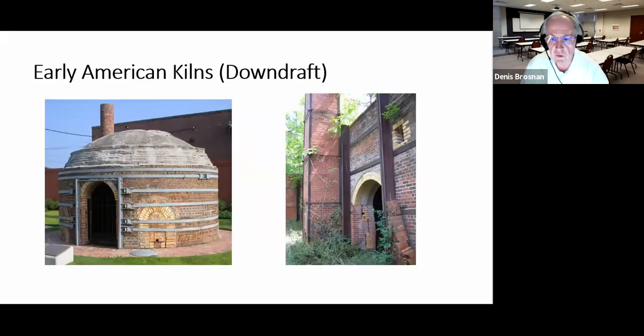Early American kilns morphed or evolved into downdraft kilns. So here's a small downdraft kiln. It's been restored. The burners were here. You can see the fire bricks forming an opening. And so solid fuel was used to burn inside these burners. And the hot gases went up toward the center, and they were sucked down through the middle using a chimney effect. So the heat went up, but then it was drawn downward, and there's a replica of a chimney, not an actual chimney here, to show how this might have worked.